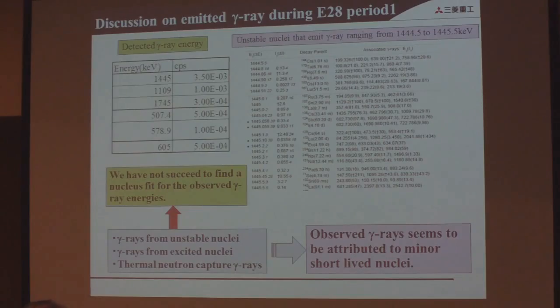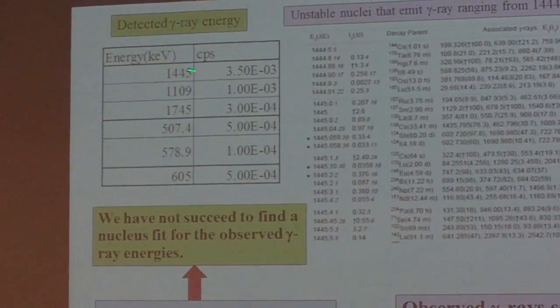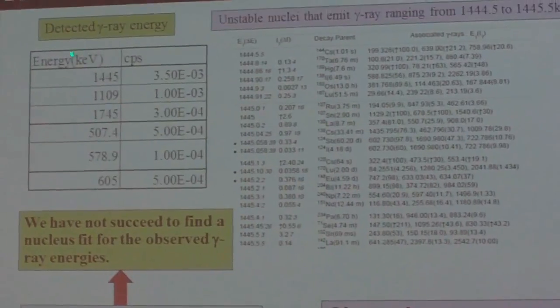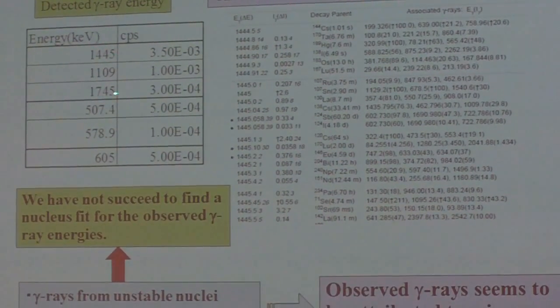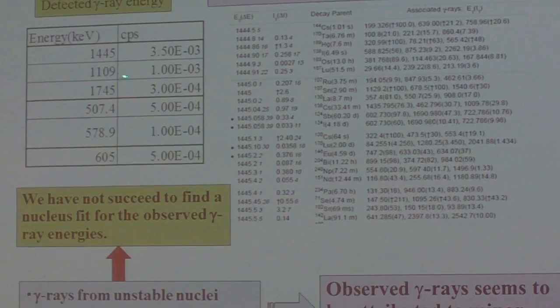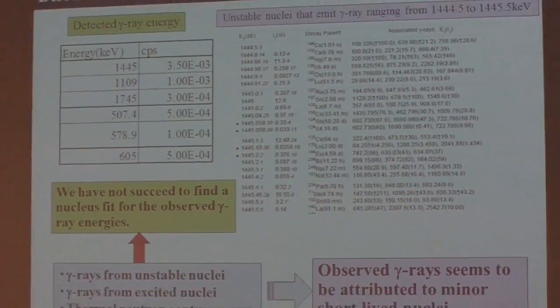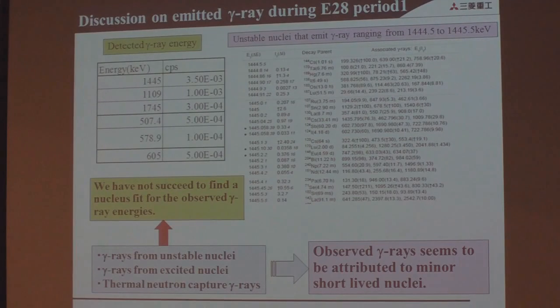And these are the detected gamma rays here. This one and this one I show you the spectrum. The other peak, not so strong but a clear peak, is here. And we investigated what species can explain this peak, but we cannot explain it from a single unstable nucleus. We searched many databases, but we cannot find one species.